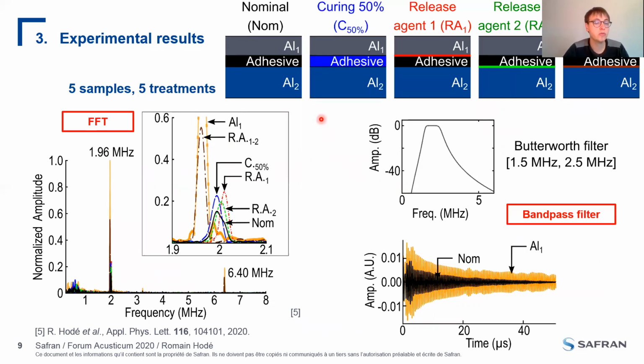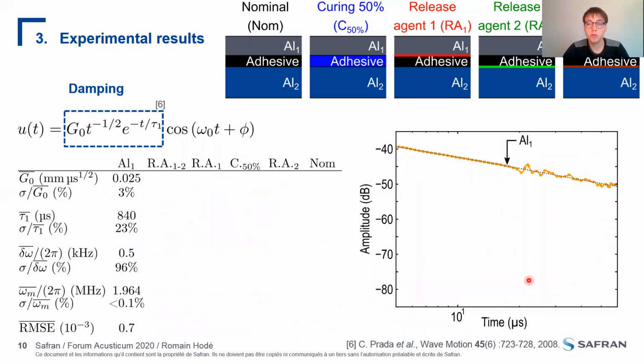So we want to use the frequency of the ZGV mode, but also to study the attenuation of these resonances. And thus, we have applied a bandpass filter on the temporal signals to filter the signals around the 2 MHz. And we can obtain this temporal signal after filtering, in the case of an aluminum plate and in the case of the nominal case. And we can plot this attenuation as a function of the time, but in a logarithmic scale. And thus, we can clearly see that we have a good accordance between the experimental attenuation and the theoretical model that was developed by Claire Prada.